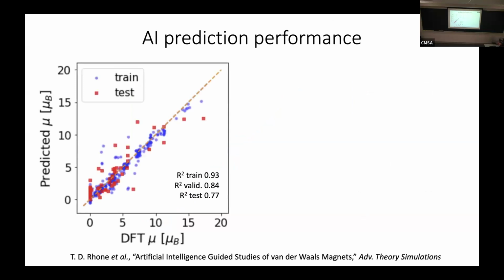So what we can do is then collect our results, create a model, and compare our predictions with the actual values. And we can plot the calculated magnetic moment on the horizontal axis and the predictions of the magnetic moment on the vertical axis. And we can have this dashed line be the perfect prediction line. It's not a fit, it's just a perfect prediction line. Because all our training data and our test data are falling close to this perfect prediction line, we can claim our model accuracy is pretty good.